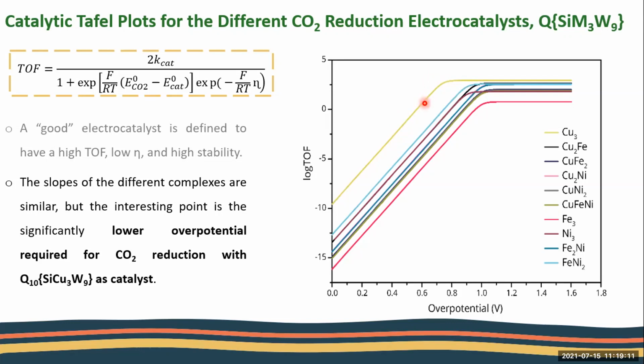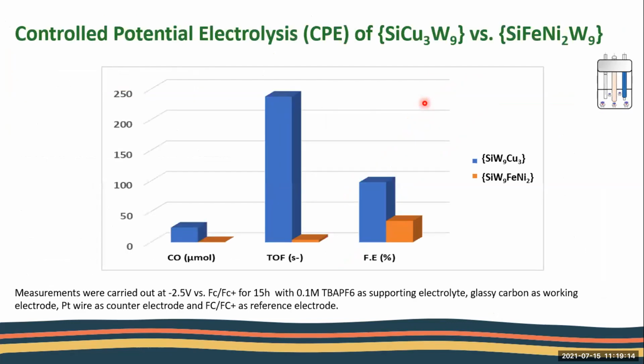So from this point, we decided to check the reaction. We went to our undivided cell, bubbled CO2, and checked the products that we got with both catalysts. If we compare the copper 3 catalyst and the iron nickel 2, you can see that we got a very beautiful amount of CO with the copper 3, equal to 24 micromole of CO with 98% Faradaic efficiency. But when we measured the product with the iron nickel 2 complex, we got very little CO. That was a little strange to us because in this complex we also had a catalytic peak.